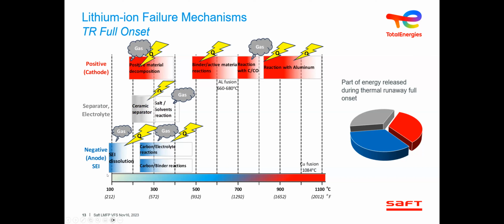You will have initially a destruction of the solid electrolyte interface, which is why it's important to note this structure onto the anode. As soon as you have destruction of this, you start a chain reaction of heat buildup that leads to other components failing. Your separator can be next and leads to a hard short circuit, which engages the cathode. Once the cathode is triggered, and that's nickel metal oxide, you have a lot of oxygen being released into the reaction.